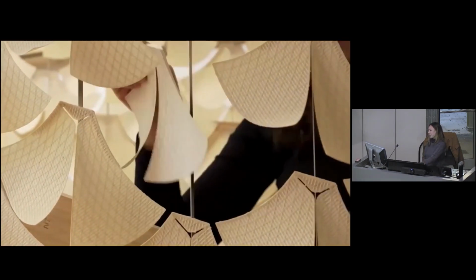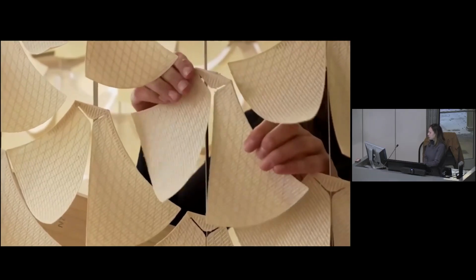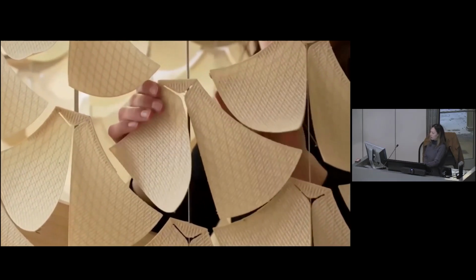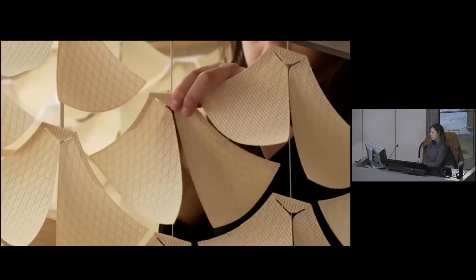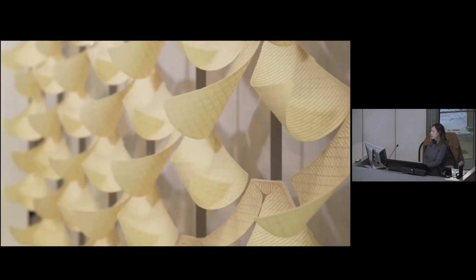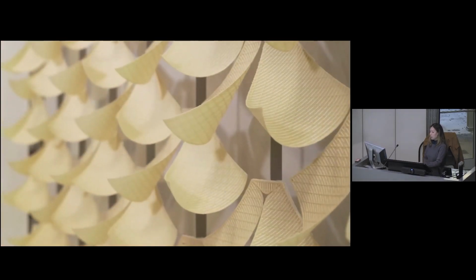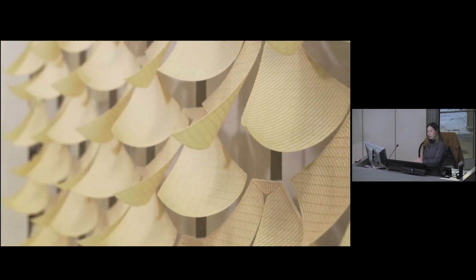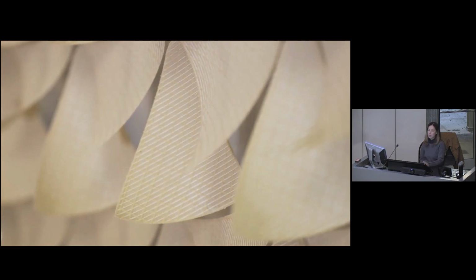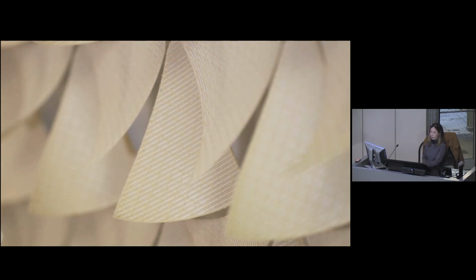All of the 4D printed elements were then pre-assembled at our lab onto thin aluminum strips through this integrated 3D printed press fit connection. And after each window was pre-assembled, they went through a short testing cycle again, just to make sure that there's no defect before the installation.